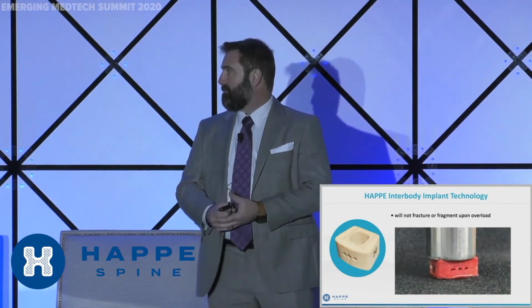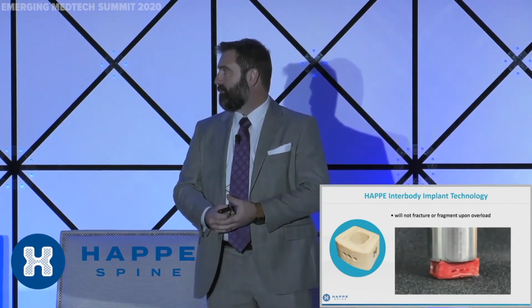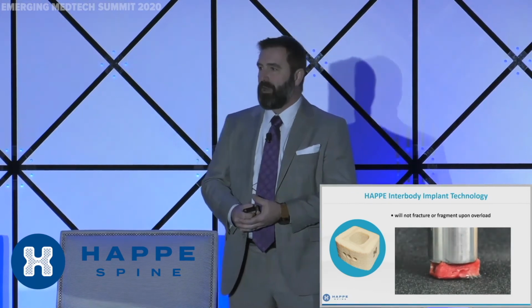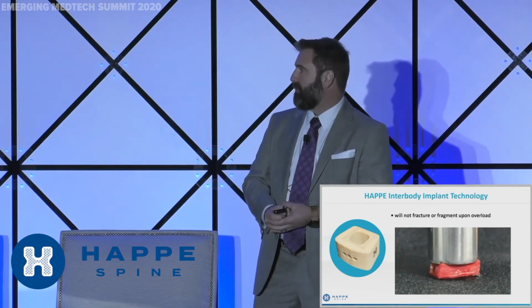Through a very extreme test, we proved here that we do not fracture even under maximum compression. Independent lab testing done for ASTM standards and impaction testing have shown that we've met our design criteria.